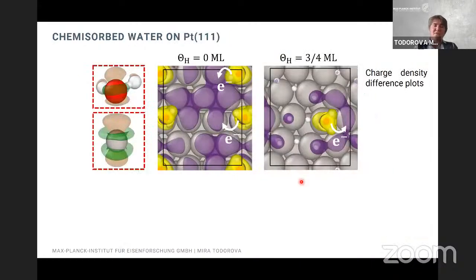Because density functional theory, of course, allows us to further analyze the system and look at the electronic structure, this is exactly what we did. And here, what you can see is charge density difference plots for various coverages. And here on the side, we have also taken, so these are two top views, and this is a side view just of the platinum atom from the surface and the water that is sitting exactly on top of it.